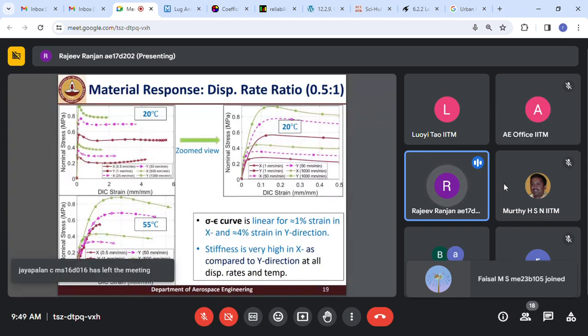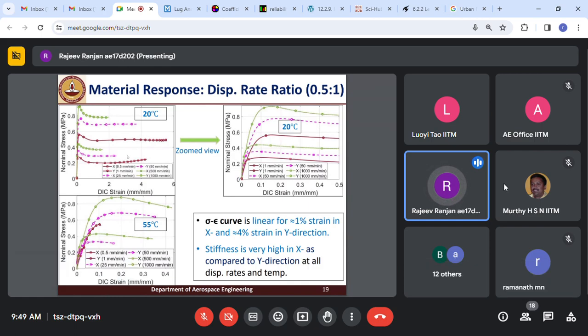During biaxial loading with a displacement rate ratio of 0.5:1, we observed these test responses, where again the dependence on displacement rate as well as temperature was there. Here also, with an increase in temperature, there was a large decrease in the failure strain.